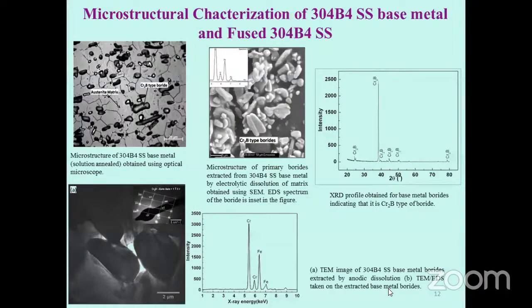Now coming to the microstructural studies of this borated stainless steel. This is the base metal microstructure. Here is the austenite matrix. You can see the grain boundaries of the austenite, and these black particles are the borides. We have boron added to this austenitic stainless steel because of its low solubility in the matrix, so it comes out as boride precipitate during solidification. During welding, these borides go into the liquid stage and solidify again, so in the fusion zone the morphology will be different. Now we have extracted these borides from the matrix and characterized them.